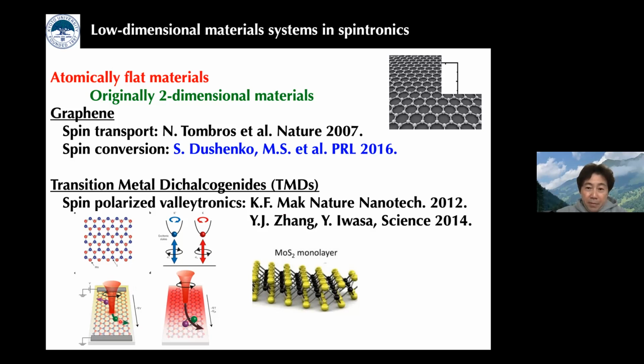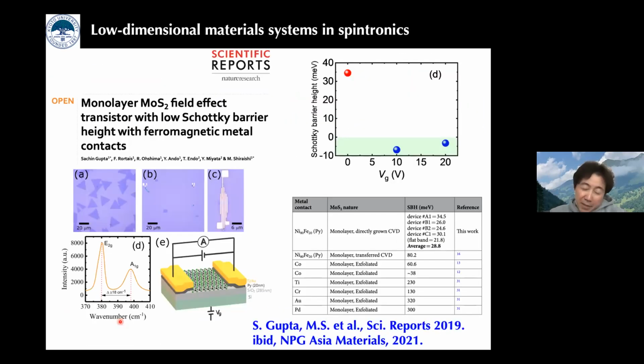So my group, I myself, was a little bit hesitating to enter this TMD field, but luckily I was able to work with an excellent Indian postdoc, and he established the formation of a low Schottky barrier height system between single-layer TMD and ferromagnetic metal. So here, the ferromagnetic metal is perpendicular, PMA, or in-plane, both. So now we are doing some interesting works using TMDs by combining with various types of ferromagnetic electrodes.